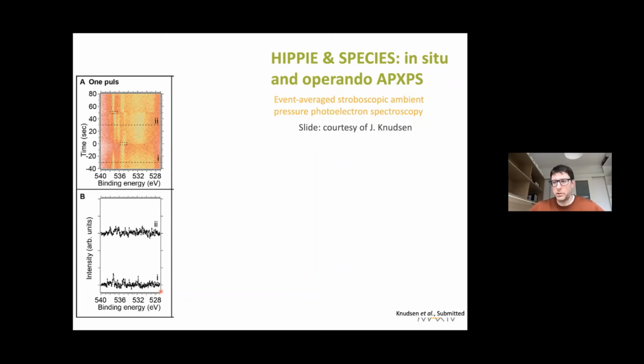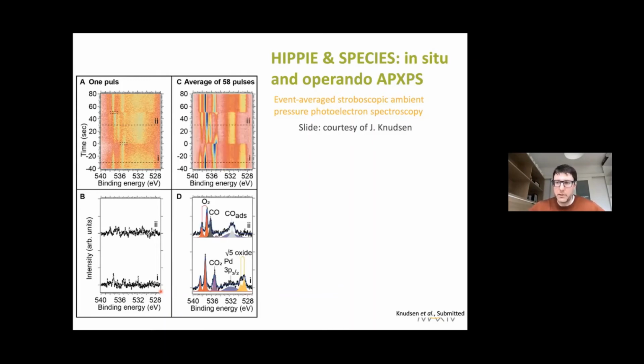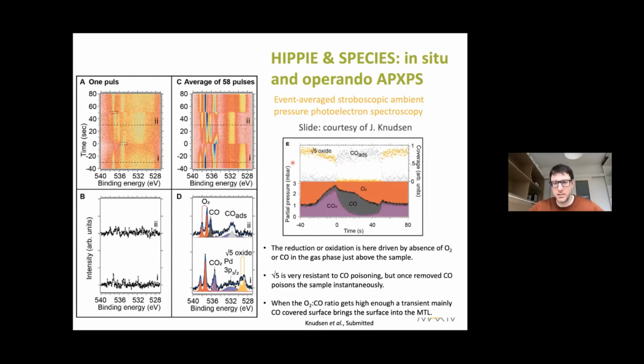Fortunately, if you repeat this experiment over and over many times, and by many, I mean tens or even hundreds of times, with thousands of spectra, and then you use a very clever technique of aligning them, you can average and substantially increase statistics. And then, from the same spectra, you suddenly get all of the information that you need. You can fit it with the peaks that you want according to the chemical composition of your surface, and get the correlation between the gas phase, which is at the bottom, and the surface composition, which is shown at the top. Then you have the whole story of what's happening within the CO-rich pulse, oxygen-rich pulse, CO-rich pulse, but also what is going on in between, how the surface is switching between two different phases.